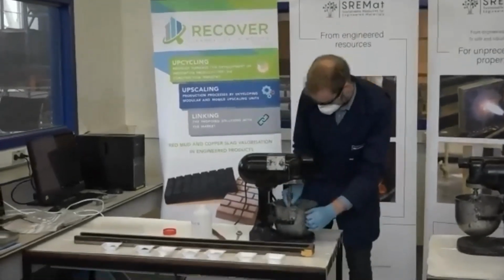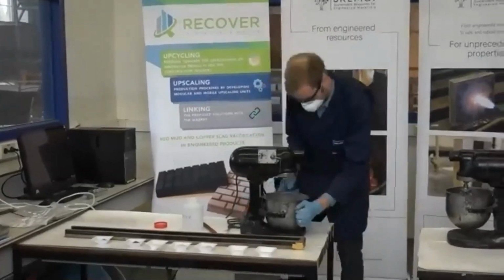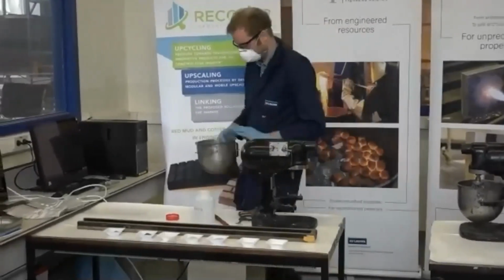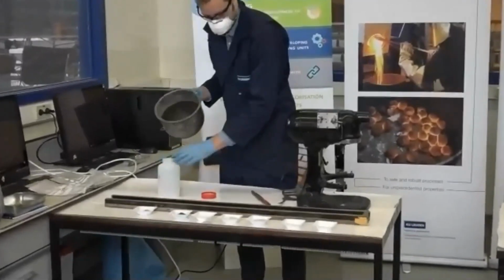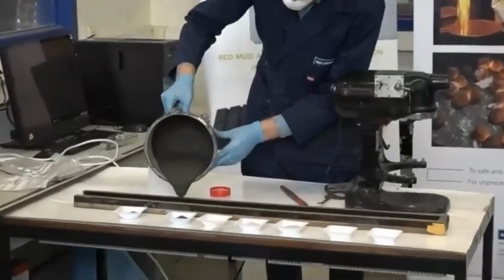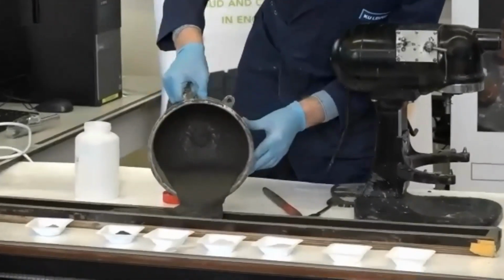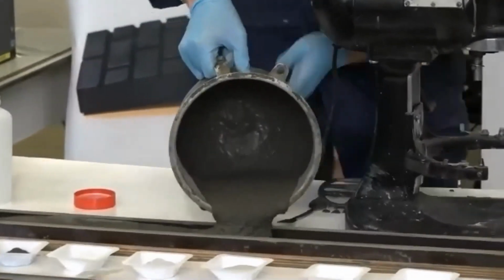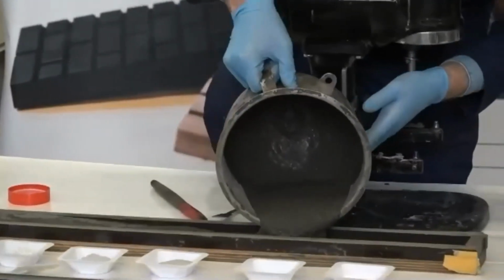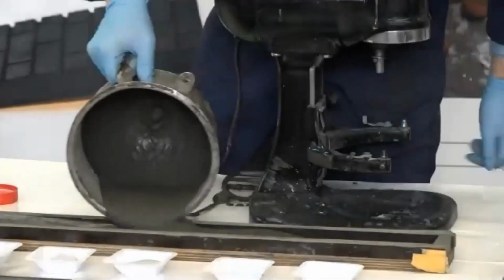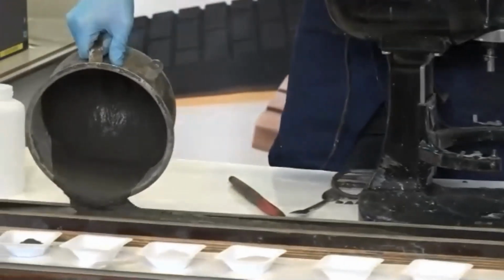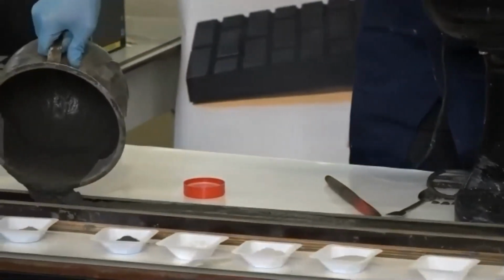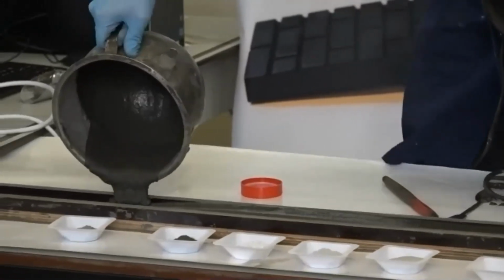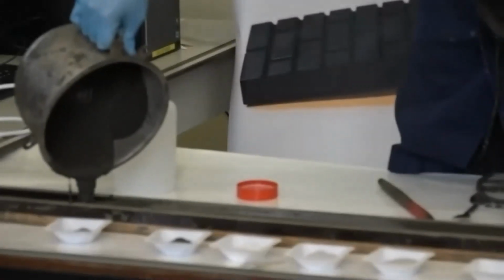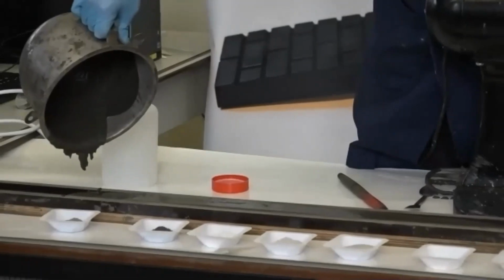And now the next step is basically to just cast this paste or this mortar mix in the mold, in that slab. And you can see how well it flows out of the mixing bowl. And we didn't use a lot of activator in this case, but as mentioned at the beginning for the mix design, the additives that are working for cementitious systems also work in these hybrid binders, because we can use an alkaline activator of lower molarity, and they are basically stable in this environment. So you can see how self-compacting this mix is.